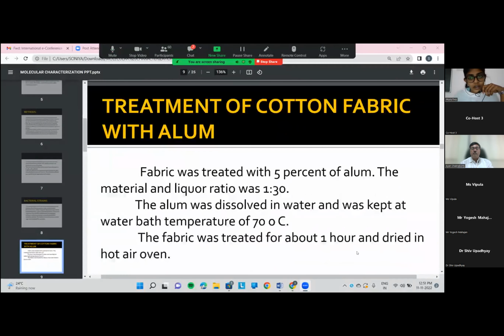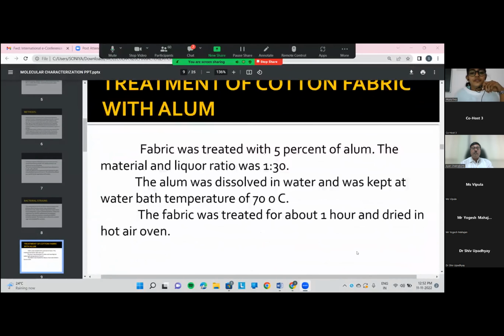Treatment of cotton fabric with alum. Fabric was treated with 5% alum. The material to liquor ratio was 1:30. The alum was dissolved in water and kept at a water bath temperature of 70 degrees Celsius. The fabric was treated for about 1 hour and dried in a hot air oven.